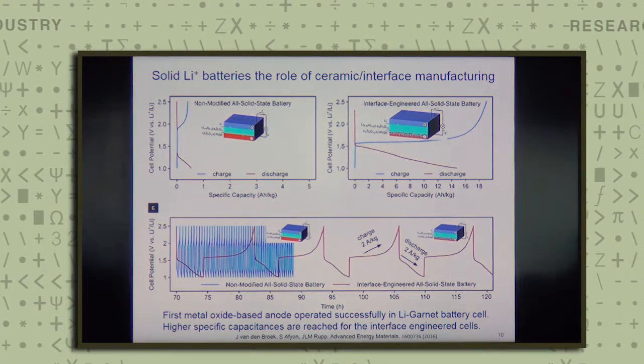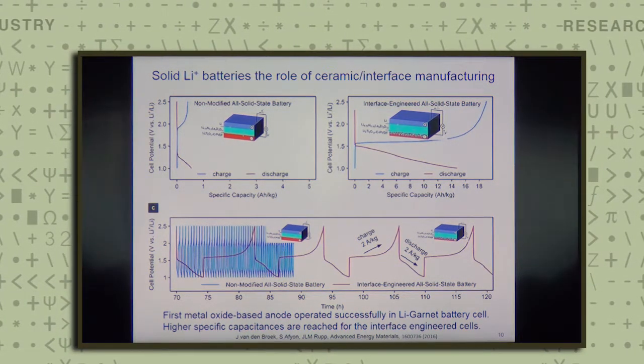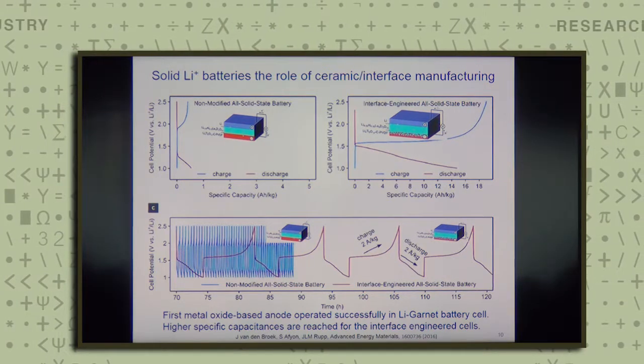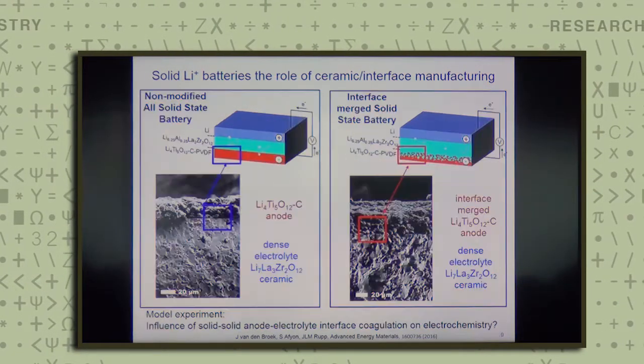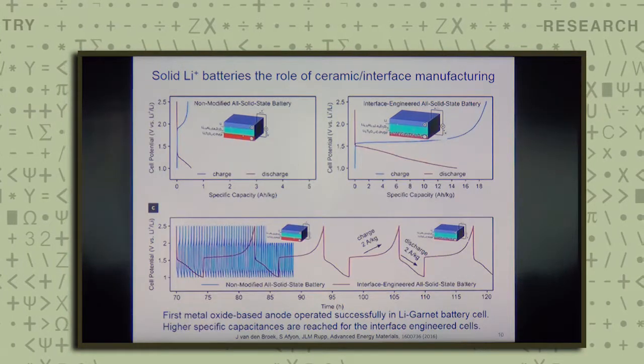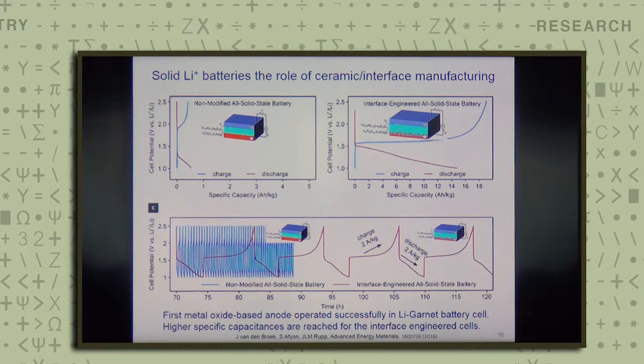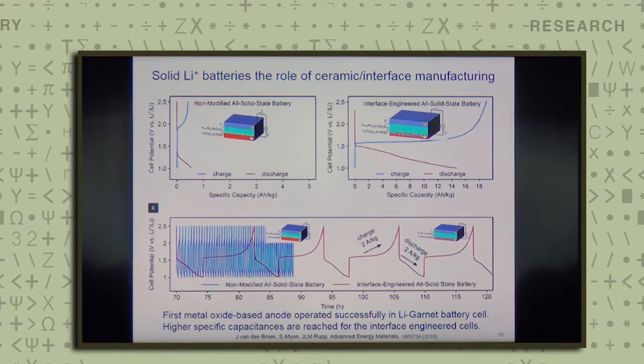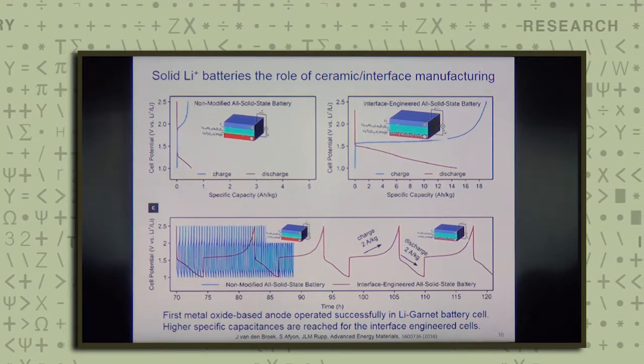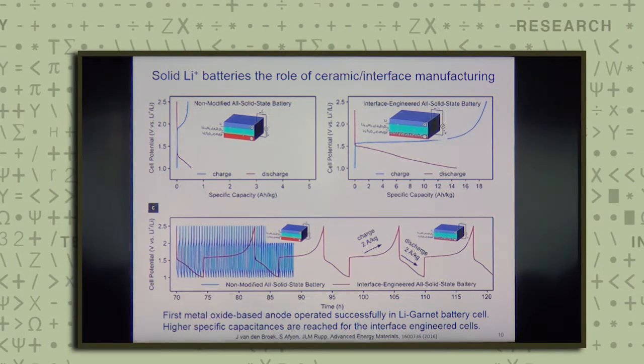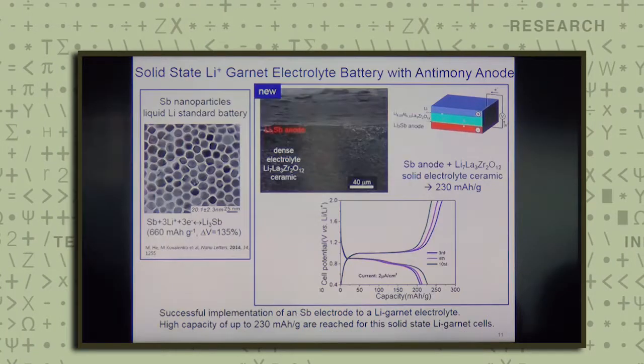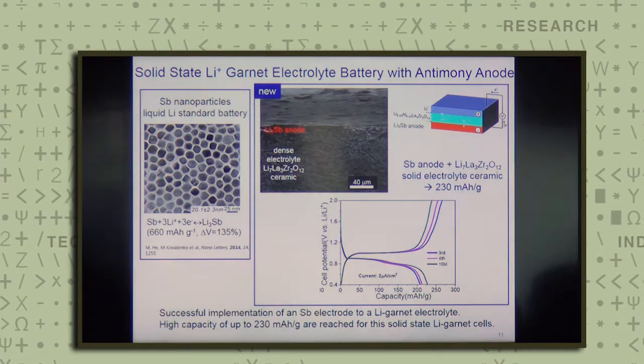To just show you in a little slide, it depends very much how you sinter the interface in these ceramics, because if you have the dense, sharp structure, we can see that the battery performance actually is rather low in the cycling, and the moment we make these coagulating structures of those two dense electrode solid-state lithium garnet interface, we can see that we can ramp up the performance. Now still, of course, there's a way to go to come even to higher performances.